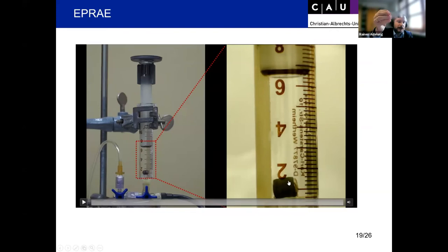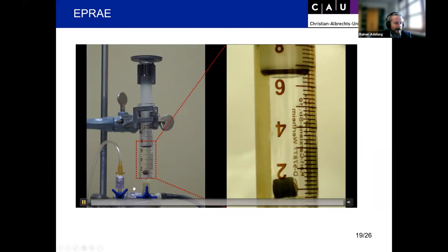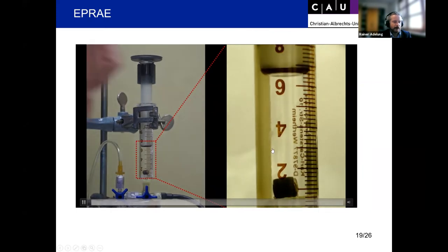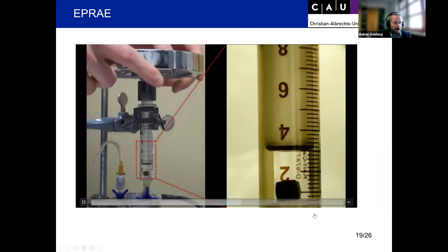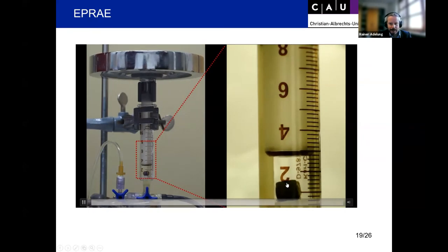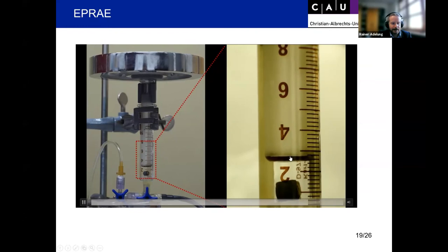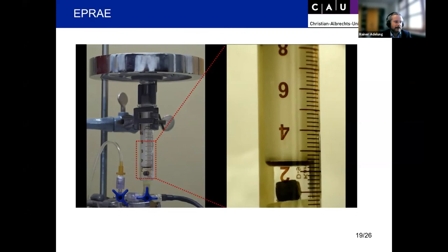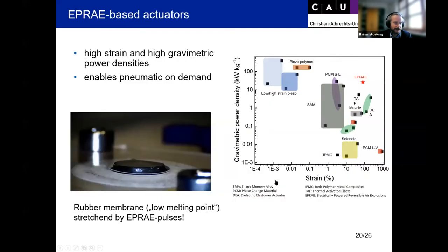You can apply this now by placing the aeromaterial inside a syringe filled with liquid nitrogen. These aeromaterials are extremely lightweight — the whole thing weighs just one milligram. But if you apply power pulses, you can move up the syringe piston by the air expansion, against gravity. To test this further, you place two kilograms on top of this one-milligram material, and the actuator doesn't care — it still pushes up the piston, moving the two kilograms upward. Comparing to other materials, this electrically powered reversible air explosion is advantageous in terms of strain and gravimetric power density.